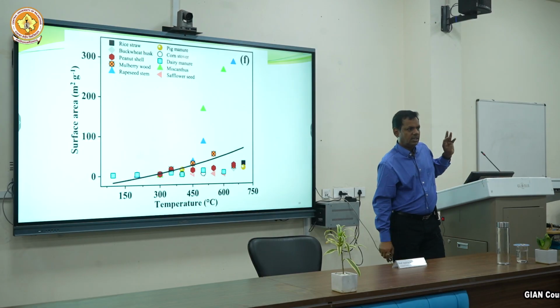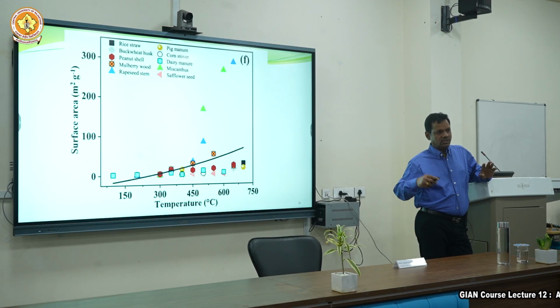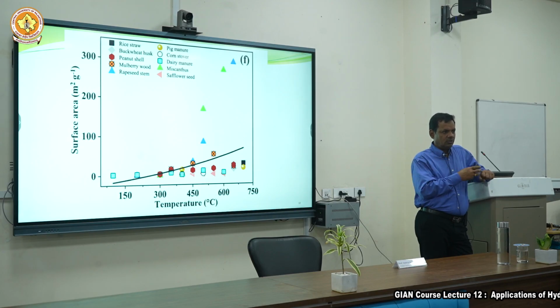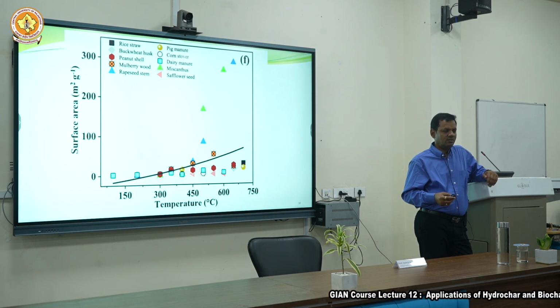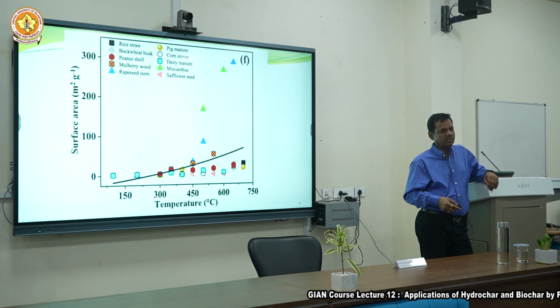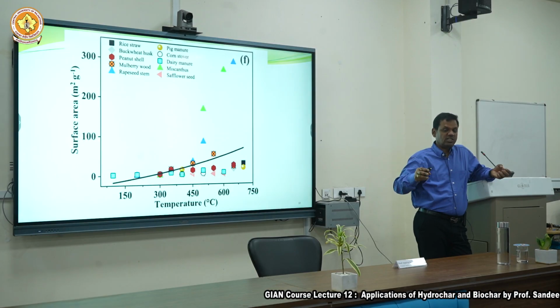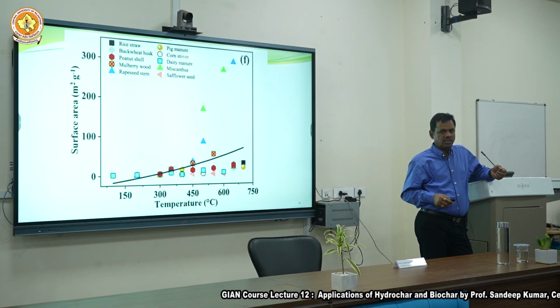Now hydrochar, low pH. Why low pH? Again think of the reaction medium. Biochar, things are going out. Hydrochar, water is doing hydrolysis and keeping organic acids inside. When you do hydrolysis, sugars and organic acids will come out, and they are still staying there, contributing to pH. So that's why it keeps low pH. Pyrolysis, more temperature, more carbon and volatiles going out, more ash components are staying there. So you will say it's close to basic.